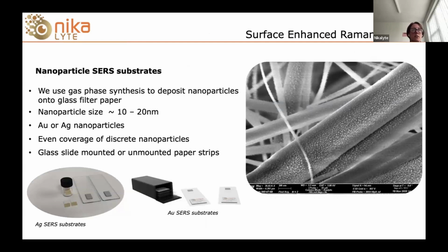So Nikalyte substrates, we use our own gas phase synthesis technology to deposit gold and silver nanoparticles onto glass filter paper. So this image here is a gold coating, gold nanoparticles on, and you can see the fibers of glass. We also have a silver product as well, looks very similar. The nanoparticles have a size around 10 to 20 nanometers, and you can see that beautiful uniform coverage. There's no clumping there at all. There's coverage over all the fibers. And you can see the ones lower down in the structure as well that are coated.